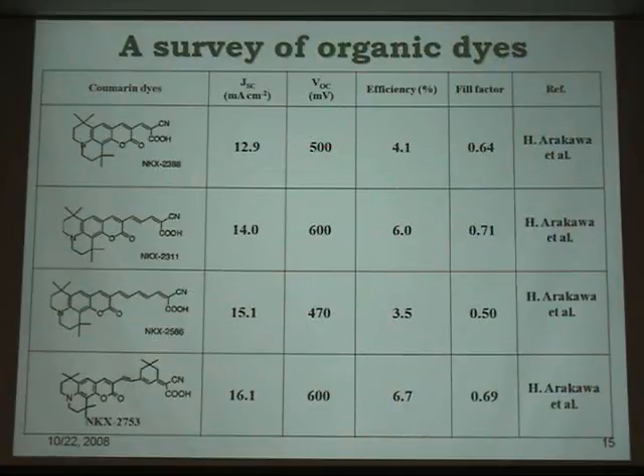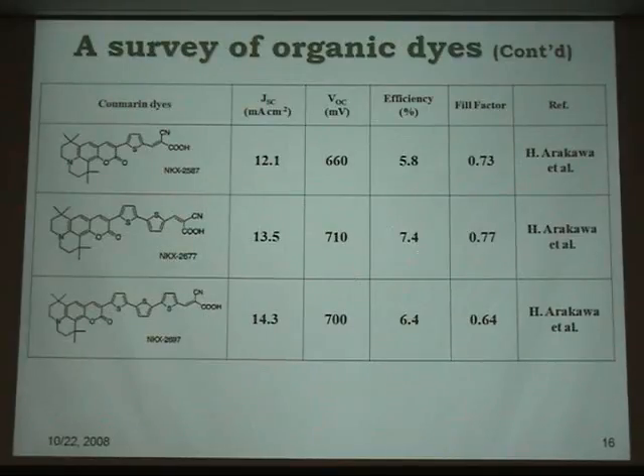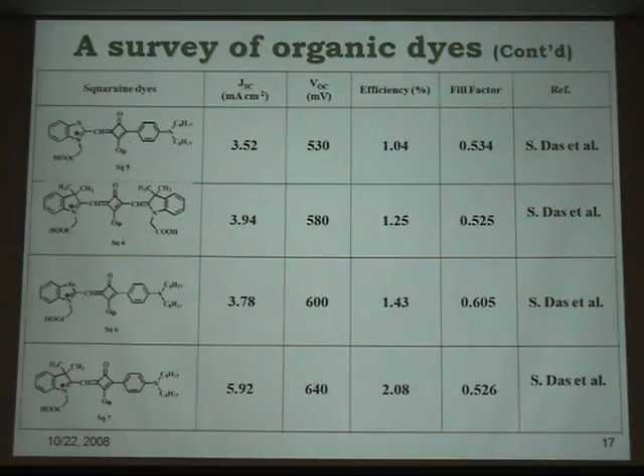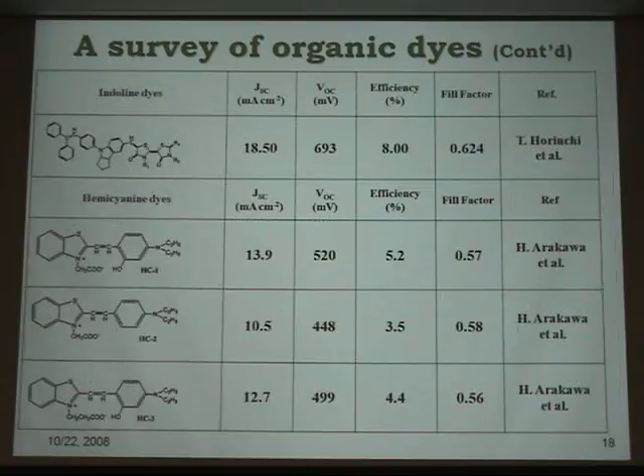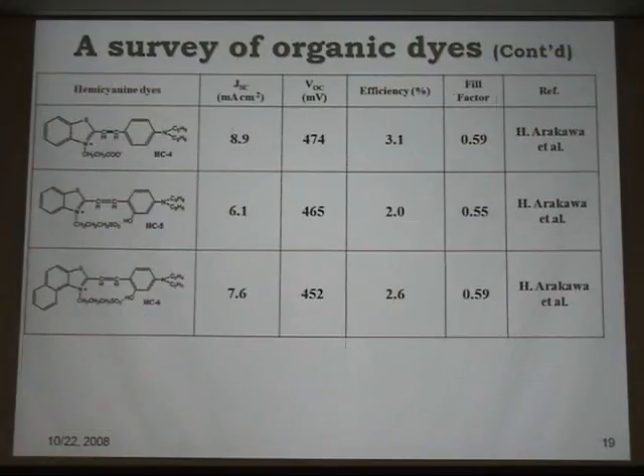The efficiency we're talking about is around 6% or so. And here you have 7, but on the other hand, some of the coworkers have come up with very high efficiency dyes. For example, with the indoline series, you can sometimes exceed 8%. And as you also know, a professor at Korea University also achieved more than 8% with organic dye. So this is well-known literature, and I don't have to get into it too much.